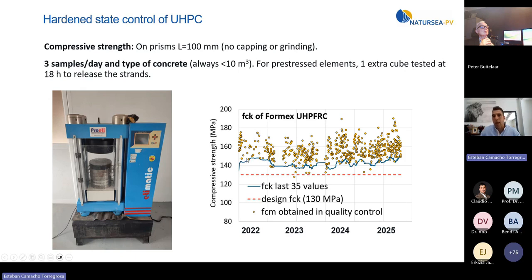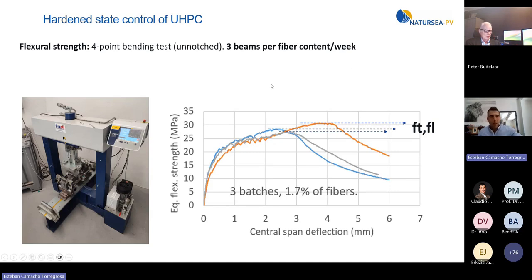Here you can see a figure of the latest results in the factory, how the characteristic compressive strength has this variation. You can see the red line and how it is over the 130 megapascals characteristic strength required by the French norm. Well, the flexural strength: despite that it is not necessary to do a weekly or monthly flexural strength control, we do it because for us the performance of the fiber is absolutely relevant, mainly in non-reinforced elements, but also in reinforced elements because they control the crack width. And we found out that it's better and more economic for us in the long term to control this.